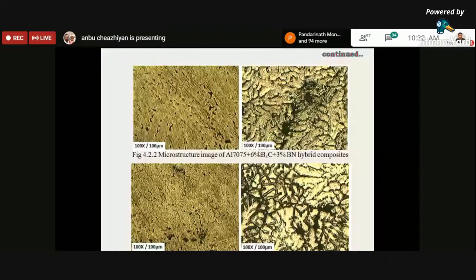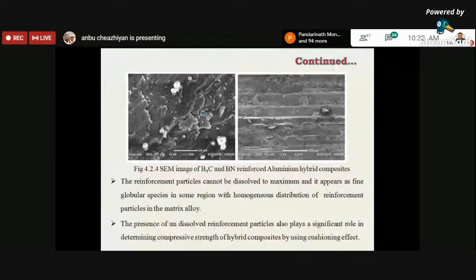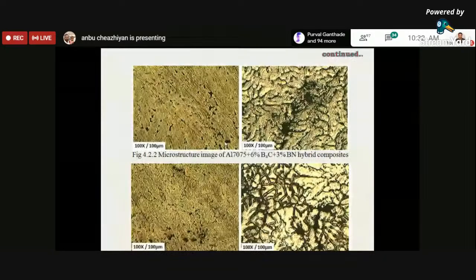So it can be dissolved fully, so that it appears as a fine globular species in the matrix. And this can also be used as a good behavior in compressive strength. It also shows that the matrix aluminum shows a fine interdendritic pattern of grains, which are precipitated at the grain boundaries.